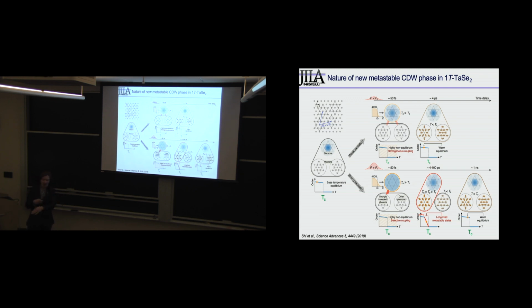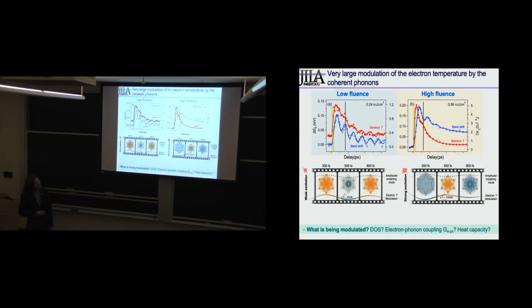You can sort of see that in the data depending on what you're exciting. And so the only way we can explain it is if there's strongly coupled phonons and other phonons, and we're interacting much more with the strongly coupled phonons, and then the other phonons heat up over time. And I'm not doing a great job of explaining it because I wanted to show just one more piece of data that's not even submitted for publication, but we'd love to explore in other materials, is normally